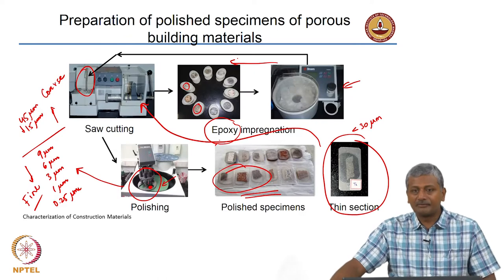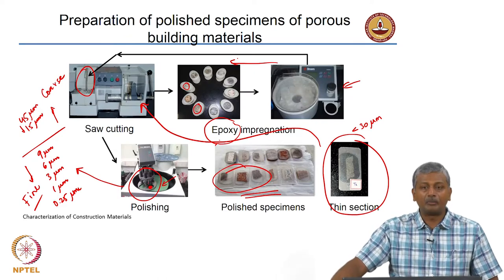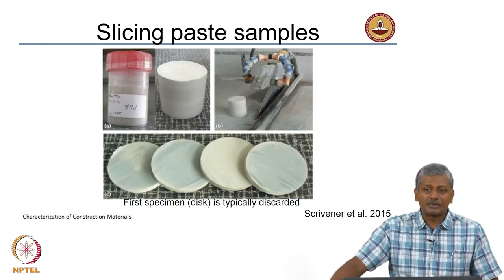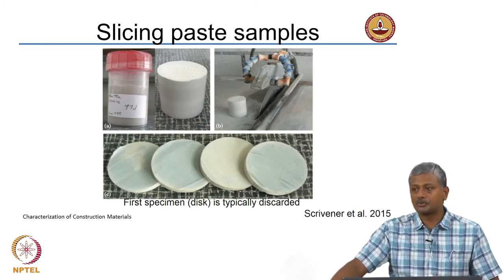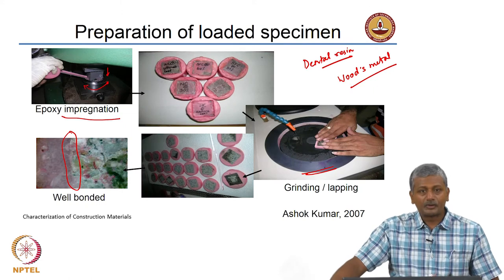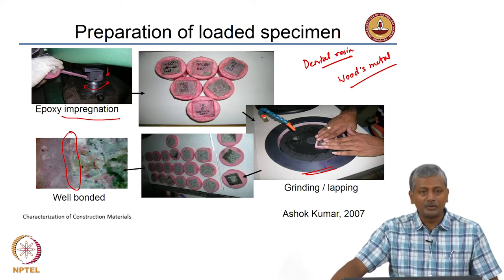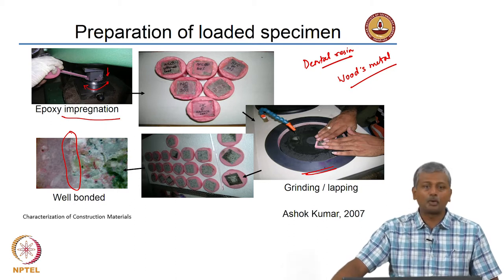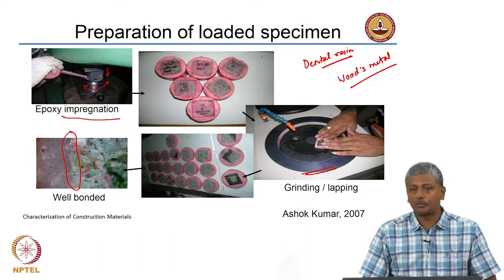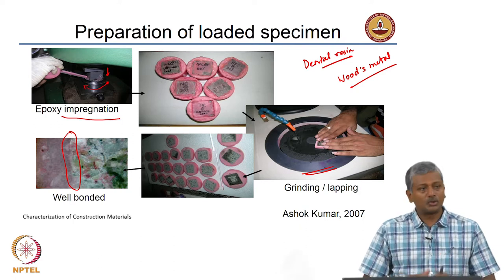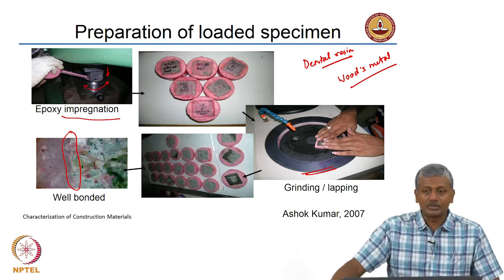There are several aspects involved in terms of polishing specimens in porous building materials, and sometimes you can prepare materials specifically for the purpose of microscopy. We also looked at cases where loaded specimens could be used — you can actually preserve the structure under loading by using an appropriate epoxy that is able to encapsulate and impregnate the porosity and the cracks to ensure that the cracks do not close after unloading.